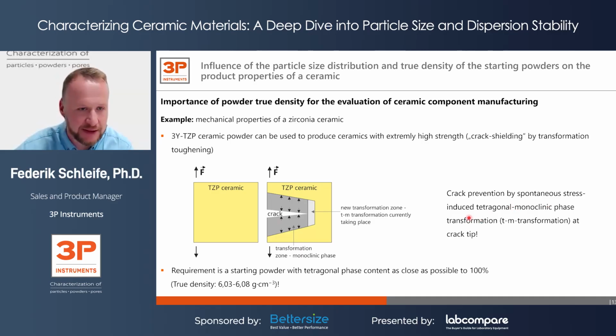When there's a crack, this crack leads to a spontaneous stress-induced tetragonal to monoclinic phase transformation, also called TM transformation, at the crack tip. So due to the stress that is applied here, the tetragonal structure will undergo a transformation into the monoclinic structure. As you remember, the monoclinic structure comes with a 3 to 5 percent larger volume. And this increase in volume spontaneously prevents the crack from traveling further through the entire ceramic workpiece. If it were only a monoclinic structure, when there's a crack at one point, this crack might go through the entire piece and you cannot use it anymore.